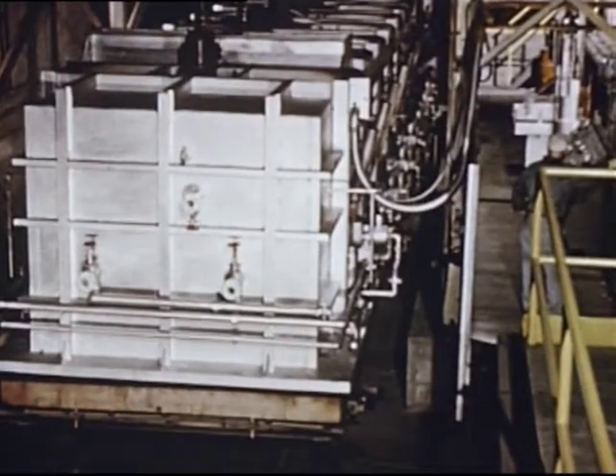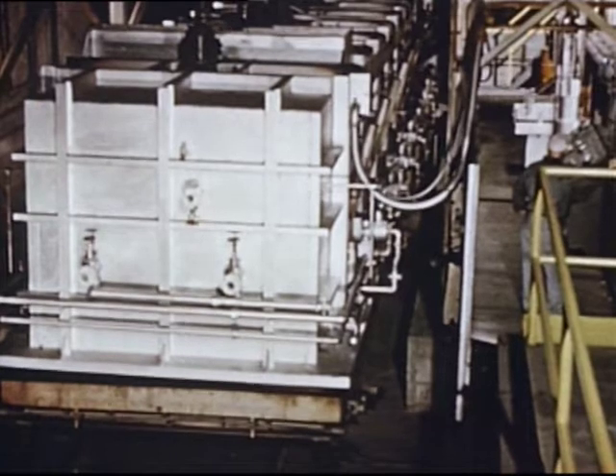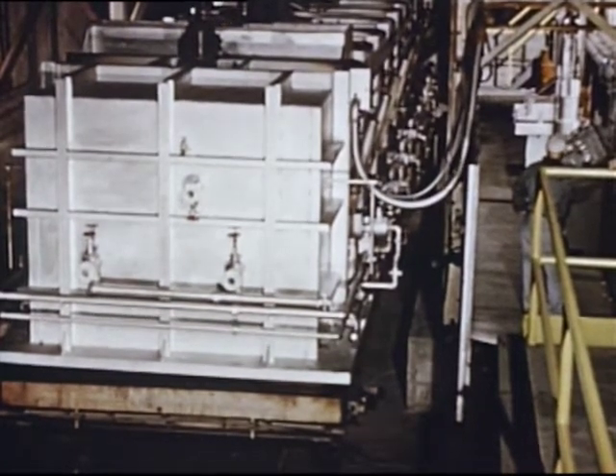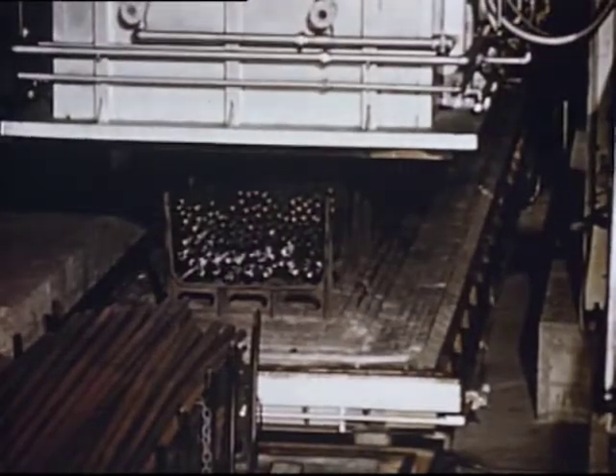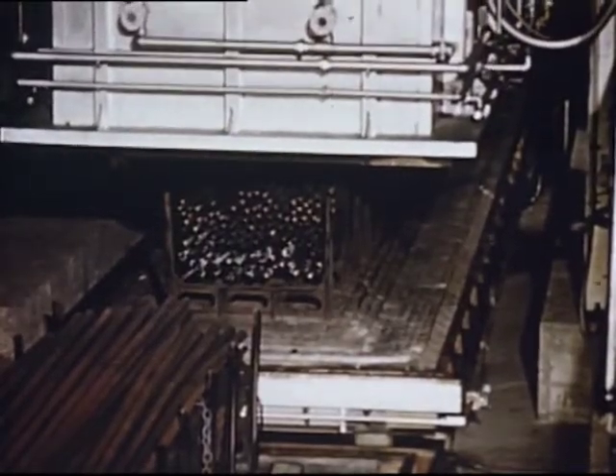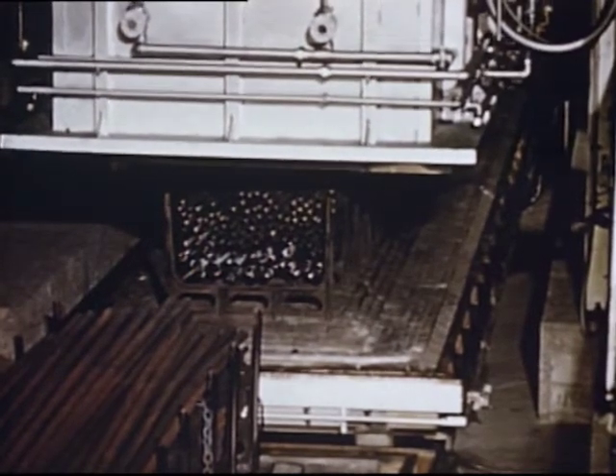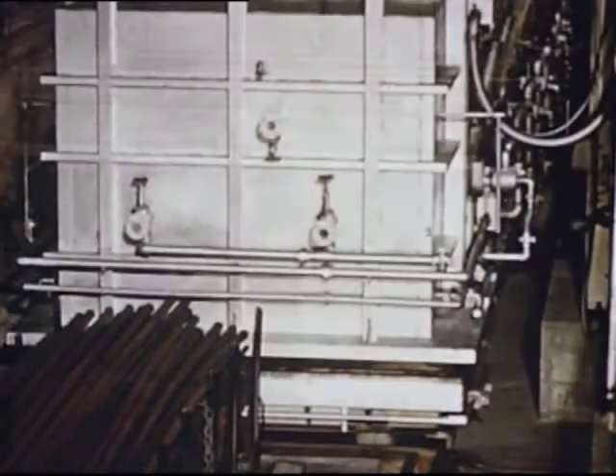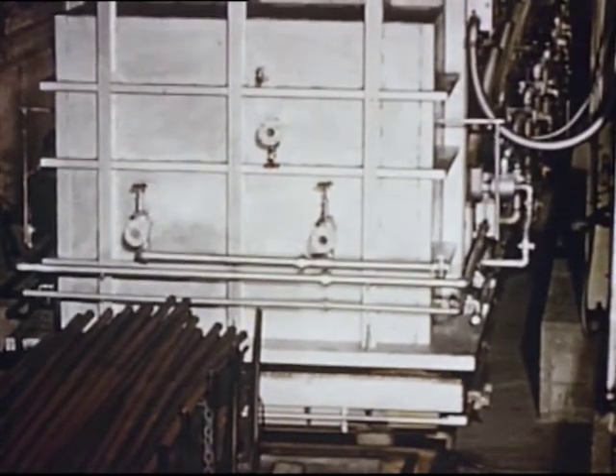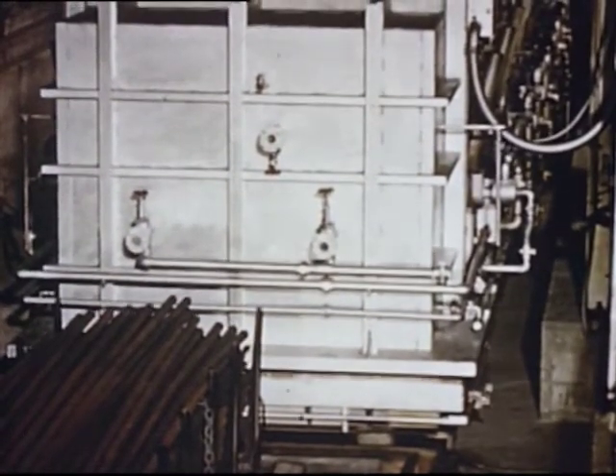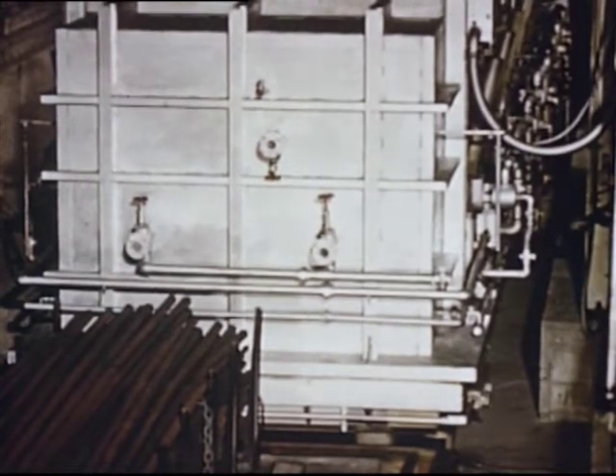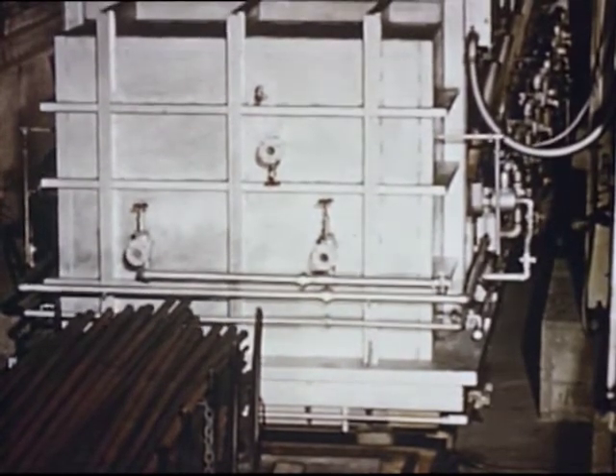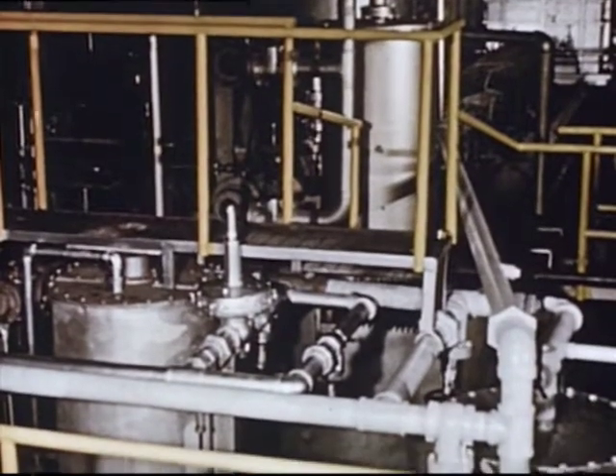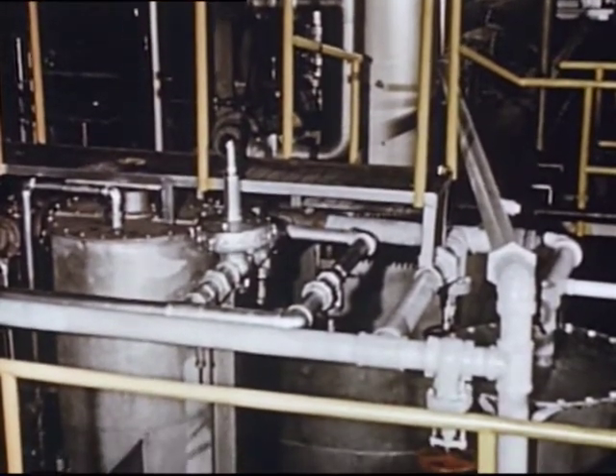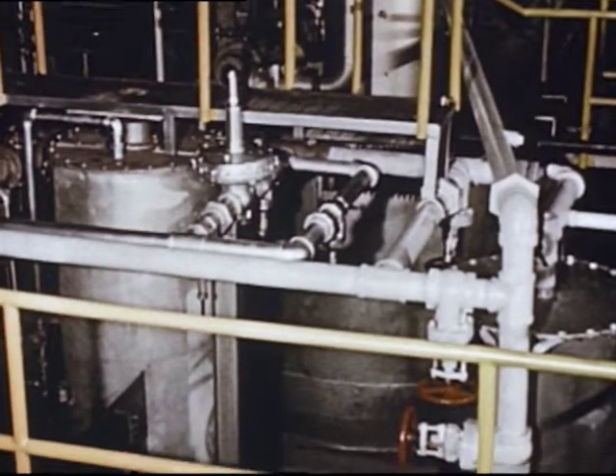Some steels requiring special structures are annealed in this revolutionary new furnace, unique among producers of seamless steel tubing. This furnace makes it possible to program anneal any type of low alloy and carbon tubing to obtain any structure possible with a particular grade of steel. The fact that these structures can be obtained in scale-free atmosphere is an outstanding development in the industry and a Michigan seamless first.